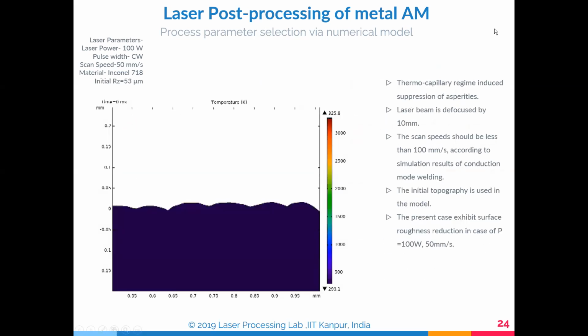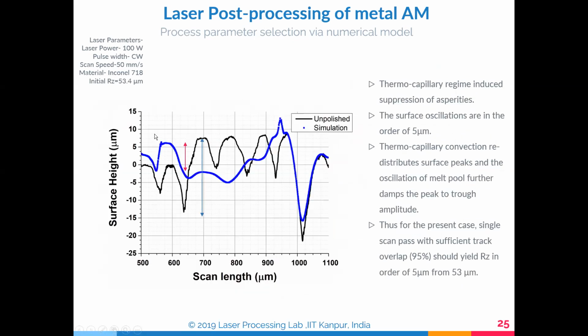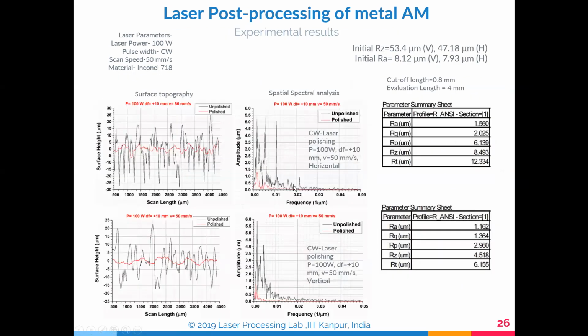We did thermocapillary induced suppression of asperities. Then the laser beam was defocused by 10 millimeters. Then the scanning speed and initial topology were set, and the experiments were done. So these are the two different cases. The unpolished surface is black and the polished simulation is blue. And we were trying to get the results validated with the experiments we conducted.